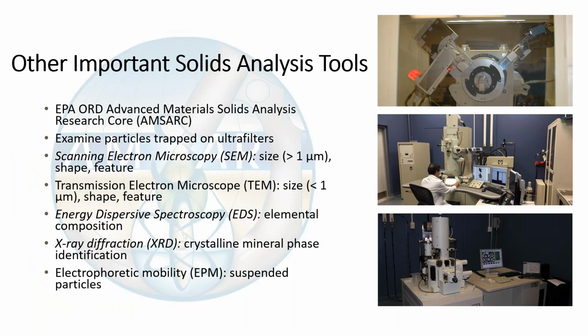And again, there are important solids analysis tools. I've sort of jumped ahead on this one, but we have some things in our lab, of course: the ultrafilter, looking at particles as they go through different particle size filtrations, and our electron microscope, which is good down to about a micron or so in size. When connected with energy dispersive spectroscopy, it also tells you about the elemental composition of the particles you're looking at. Transmission electron microscope gives you really small particles, less than 1 micron, and gives you information about shape and features,